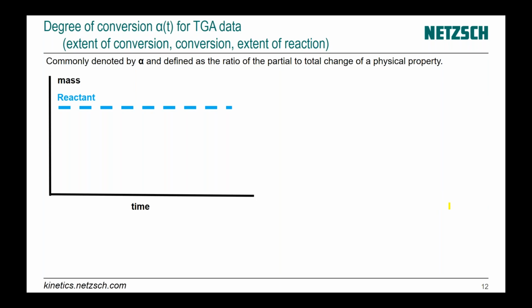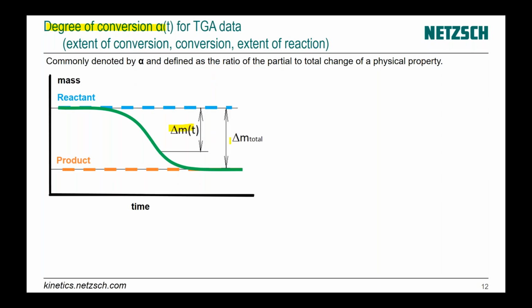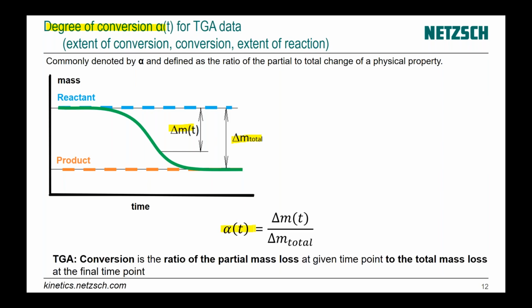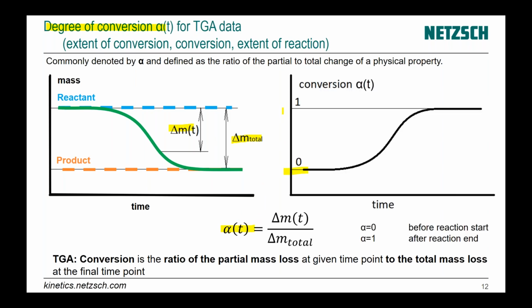Now we have totally different measurement techniques, and we should arrive at some value that describes only the chemical process, independent of the technique. This value is called degree of conversion, or alpha, and it shows what part of a reaction is already done. For example, in thermogravimetry, we have reactant and product, the mass of the product, and the measurement during decomposition shows a step. If we take the ratio of current mass loss to total mass loss, that value is called alpha, the degree of conversion—it changes from 0 to 1.